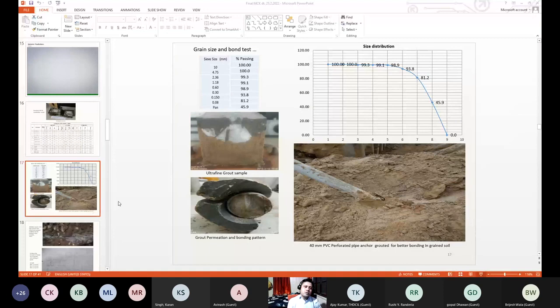Again, my aim was to protect the mountain's water, so there is no scarcity for the villagers on the mountain, because one day the water will not be there at the mountain. At rainy season the mountains get charged, but as we are frequently excavating tunnels, the water is diverting somewhere else. So we did a 16-meter length hole. The water came, then we did cement, water, admixture, and after 2 hours 50 minutes it was set by the cement only, nothing else was done